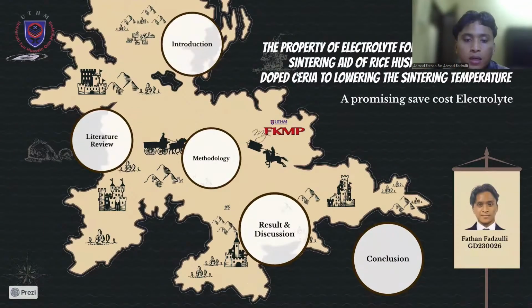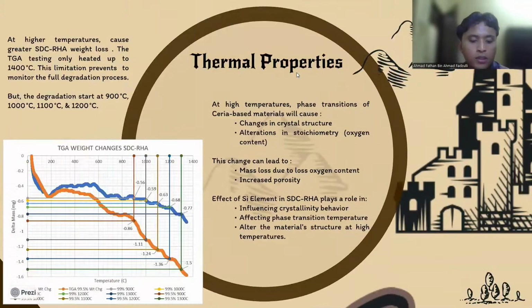Next, we go to results and discussion. TGA. For TGA, the data reveals a clear pattern. Higher temperature causes greater weight loss in SDC RHA, while testing stopped at 1400 Celsius due to equipment limits. The critical degradation window from 900 Celsius to 1200 Celsius is not fully monitored.